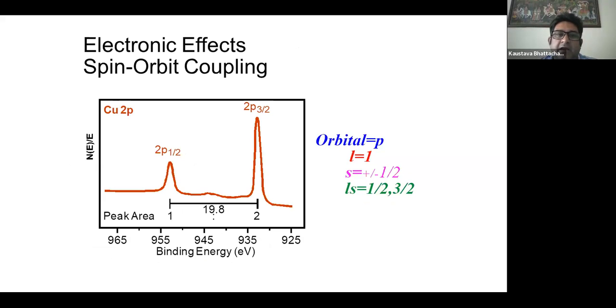Equivalently, for the p orbital, we have an L value equal to 1 and a spin value of 1/2. So we'll have two different peaks, p3/2 and p1/2. And if we go by the binding energy, 2p3/2 will have lower binding energy and 2p1/2 will always have higher binding energy. The difference in this energy is the LS splitting parameter. For copper 2p, this splitting parameter is 19.8 eV. Even if we get 2 peaks of 2p3/2 and 2p1/2, and we don't get a delta E of 19.8 eV, then it is not copper. It can be some different element, though it may come in the same region.